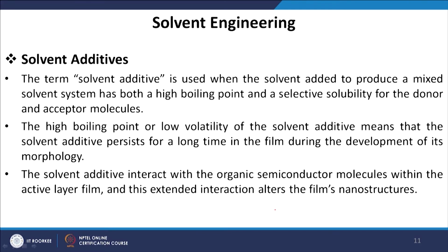The term solvent additives is used when the solvent added to produce a mixed solvent system has both a high boiling point and a selective solubility for the donor and acceptor molecules. The high boiling point or low volatility of the solvent additive means that it persists for a long time in the film during the development of its morphology. Again, as we mentioned, the strategy should be to choose a high boiling point or low volatility solvent.